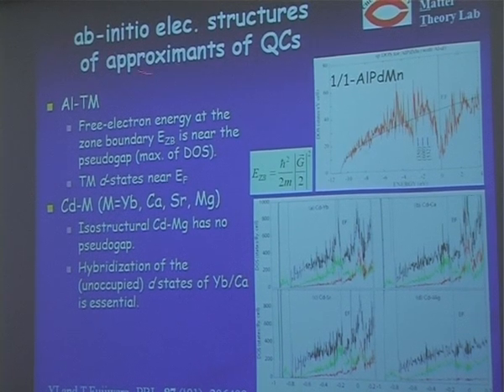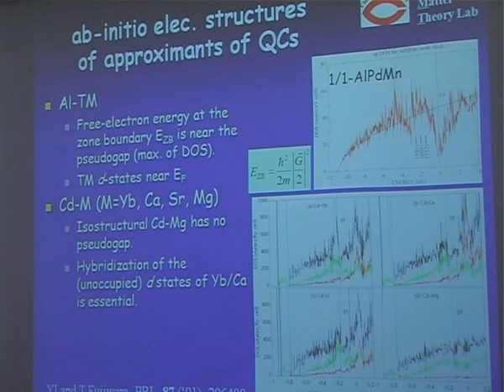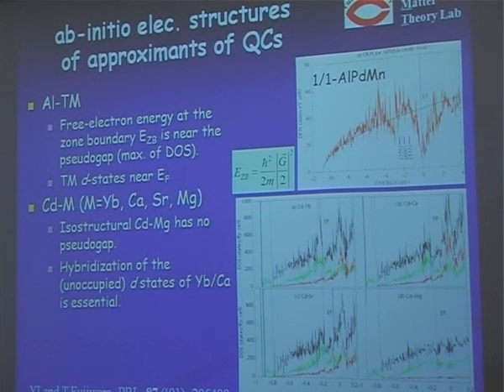But unfortunately, we are not able to calculate the electronic structure of the quasicrystal itself because of the lack of translational symmetry. So we usually calculate the electronic structure of the approximant, which is a complicated crystalline structure with a large unit cell. But we believe that the atomic structure and the electronic structure's characteristic properties are almost the same in quasicrystals and approximants. In the aluminum transition metal case, this is the cubic approximant for aluminum, palladium, manganese, and this is the calculated electron density of states. Here I showed the partial density of states without the transition metal d element component. And we have a very deep pseudo gap near the Fermi level.